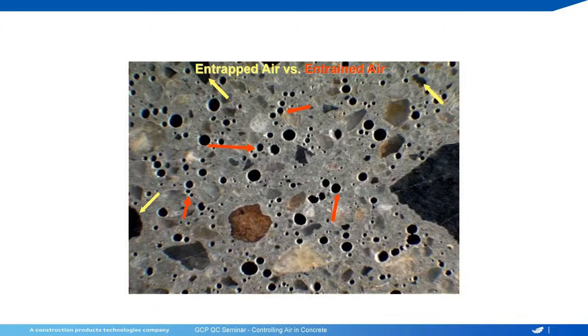So just a quick note, when you're doing hardened air, the polish is key to getting good results. So if you're getting a polish on your concrete where it shows the air voids that are raveling or ragged edges, you're not going to get an appropriate reading on the air void. That's just a side note. So here you can see the different sized entrained air, and this is obviously magnified. And then you'll see these irregular shaped bubbles that are entrapped air. And when we count air, when we do a hardened air test, we're counting all of those voids, not just the entrained bubbles, but all of those bubbles.